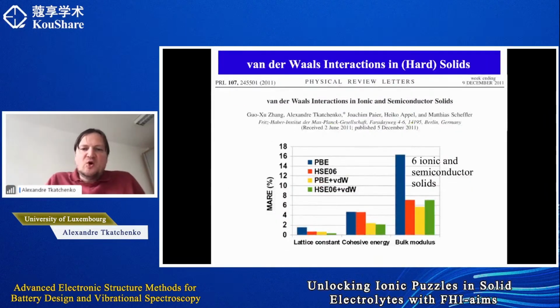Okay, so now let me go back a bit into the history as well to review what we understand actually about van der Waals interactions in hard solids. So it's not a surprise that van der Waals interactions, or dispersion interactions, are extremely important for molecular solids. For example, the benzene molecular crystal will not even assemble if you don't have the correct description of van der Waals interactions. But for hard solids, it turns out that we actually know very little about van der Waals interactions, even up to date. So here is our early work.